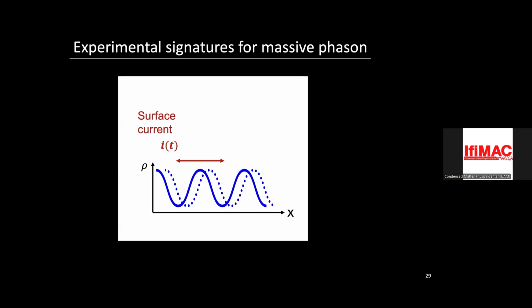So the thing that I want to now look for is signatures of this massive phason mode of this charge density wave. And there are actually two signatures that one can imagine. So the phase mode is this oscillation of the phase of the CDW. If you have a phase changing as a function of time, it always gives you a current. It's like a superconductor: it doesn't matter what the phase is, but if you have a condensate and the phase changes as a function of time, you get a current. In this case, the phase is changing as a function of time, that gives you current, and you can measure that with something like STM or point contact.